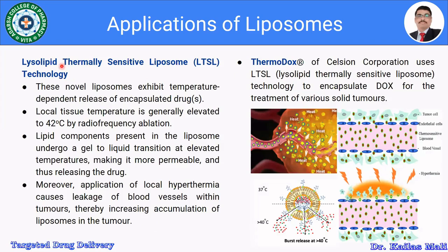Yet another technology which is available in liposomes is the lysolipid thermally sensitive liposome technology, that is LTSL technology. These are novel liposomes that exhibit temperature dependent release of encapsulated drugs. So this is a technology which utilizes temperature as a stimulus and releases the drug. Local tissue temperature is generally elevated to 42 degrees Celsius by radio frequency ablation. So here we can utilize radio frequency to increase the temperature of the tissue.